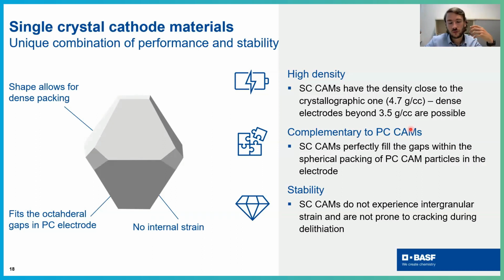So if you tune your single crystal in terms of shape and size properly, then you can actually fill the octahedral gaps of polycrystalline electrodes using your single crystal. And this cartoon here is for sure just a cartoon, but actually it's quite a real shape of the materials which you can make if you use proper synthesis. So in terms of density, this is really amazing what you can achieve with single crystals. And another thing for sure is stability. You have no grains inside, ideally, and you have no intergranular strain. It means that you do not have cracking during the cycling, which I just described before.